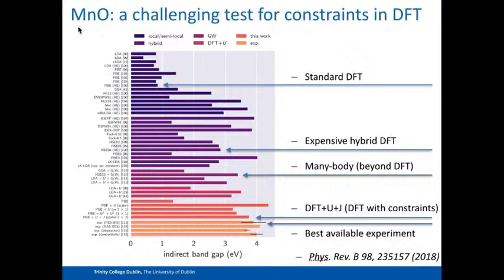So if we look at manganese monoxide, which is a very challenging system, it's not unlike the parent materials for certain high temperature superconductors. Standard density functional theory gives you absolute garbage, basically, for the band gap. So it gives you a large spread of results depending on which version of density functional theory you use, and they all underestimate the band gap with respect to the experimental band gap, which is down here around 4 electron volts. You can use a very expensive version of density functional theory. You push up the average value, but you still have a big spread.